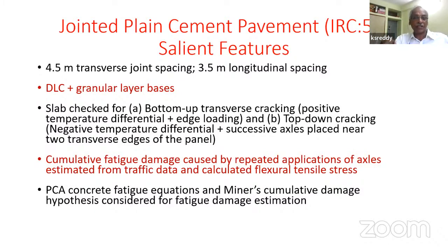So this is our performance criterion, that the theoretically calculated cumulative fatigue damage should not exceed 1 or 100%. But we do not know what it actually physically means when it is translated in terms of the number of slabs that crack, the number of slabs that have got joint faulting or other kinds of problems. So we do not have a physical visualization of the performance when we design a pavement for 30 years, what you can expect in terms of those physical problems. We're only theoretically estimating the total cumulative fatigue damage and then ensuring that it is less than 1.